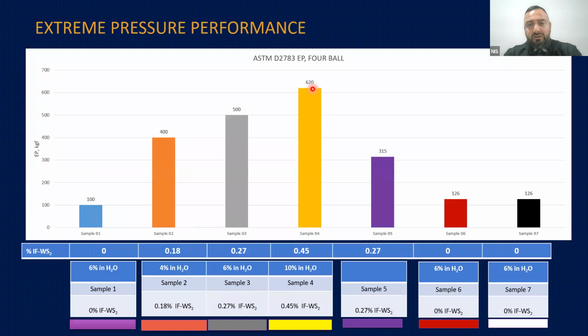Okay, this is a very interesting test. I'll stop on this one. It's also a 4-ball EP test, but what it means here is that sample 4 is 0.45% of particles, and sample 3 is 0.27% of particles in water. It has quite high extreme pressure properties. Now, when you get to sample 5, it is exactly the same as sample 3, but with a little bit of oil. So you see, the inclusion of some oil with the particles drops the extreme pressure performance, which is fine because it's just one of the tests. And this test basically has 4 balls with a liquid inside.